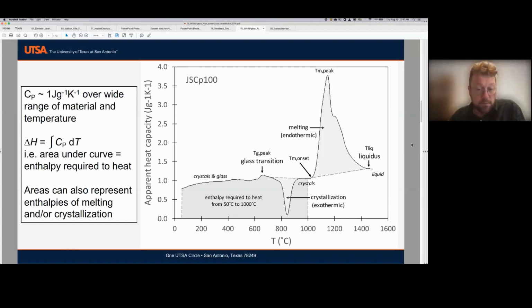We heat it up. The glassy part goes through a glass transition at about 650 degrees C, above which that part is now liquid, but it's also well below its melting point. So quite sensibly, it crystallizes. And that's what leads to that crystallization trough right there, which is exothermic. And so it appears that the heat capacity goes down because the material itself is releasing a bunch of energy that we didn't need to put into the calorimeter to heat it up. Okay, at some point we end up basically fully crystalline at around 1,050 degrees C. And then as we go above that, we start to melt. And that's endothermic, and we've got the peak there. But melting is only complete when we reach the liquidus temperature shown at the right there at about 1,400 degrees C. Okay, so that's what's happening on these graphs. The other thing, the darker shaded area there, is the enthalpy required to heat this material from 50 degrees to 1,000 degrees.